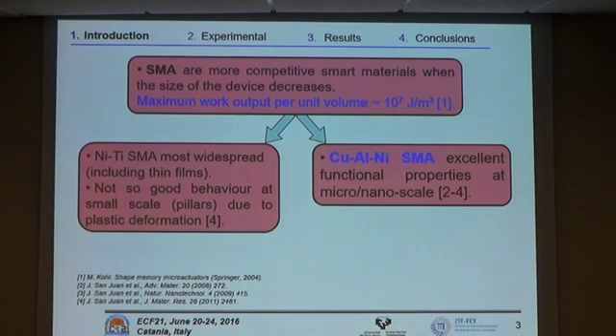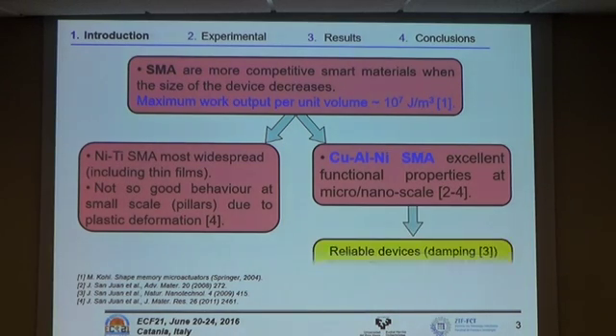And in the past, there were a lot of attempts to use the most widespread shape memory alloy, nickel titanium, in this field, including in thin films. But due to some plastic deformation, this material could not be used at a very small scale. On the other hand, copper-aluminum-nickel shape memory alloys have shown excellent functional properties at micro and nano scale. There was already some work published in the past.